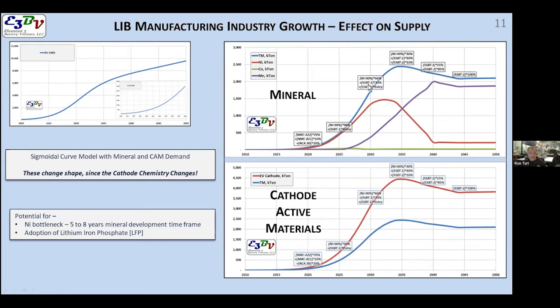Manganese is very important because it's less expensive, and more important than that, it can hold 2 lithium ions per manganese atom compared to nickel and cobalt, and most others can hold only 1. So being able to hit the higher valence state reversibly with the electrochemistry at a good potential is all part of the story here. And the high voltage cathode materials are manganese, and that is why you see a decrease in the long term.